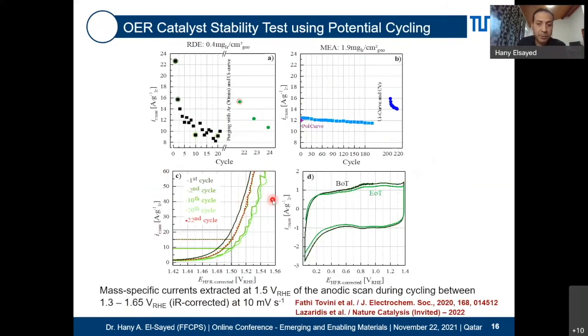The last slide I have on this topic is on the third method that also exists in literature, which is not only constant current, constant potential, but also potential cycling. So these are basically how the current decreases as a function of cycles. And this is the RDE experiment. And you can see the potential goes down, the current goes down. And if you purge with argon, start from the beginning, then you get higher current, again indicating that the surface was somehow blocked with something temporarily. And we believe that these are the oxygen bubbles, and so on.